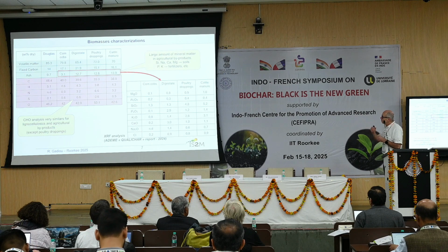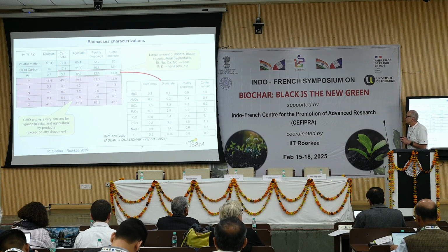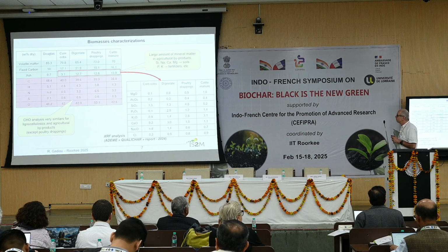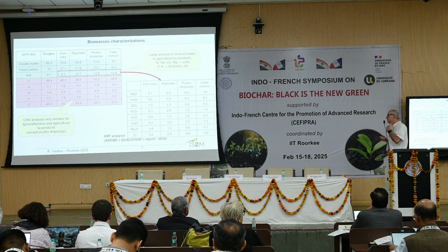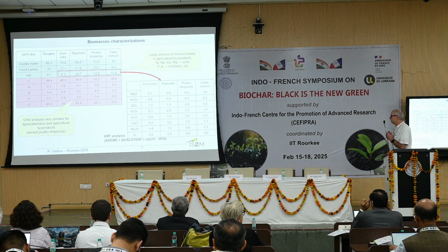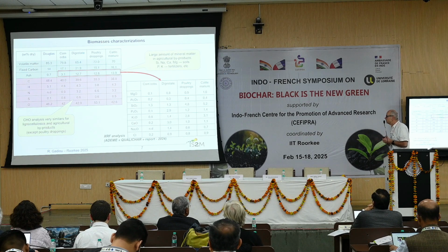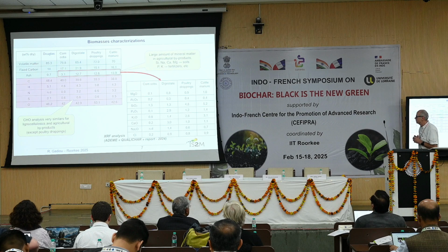And then we see that for byproduct, we have up to 14% of mineral matter in our material with very changing elemental composition, which was obtained, for example, by X-ray fluorescence analysis. And we see that, for example, for corn crops, it's a small amount of mineral matter, but mainly with potassium, calcium, and so on.